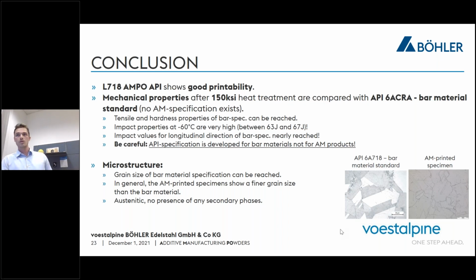So yeah, you always have to consider that this API specification is developed for bar materials and not for AM products. So we can achieve this standard, which is made for bar materials, with our AMPO, so with our AM powder. And in the end, with the microstructure short conclusion, the grain size of bar material can be reached. And of course, the AM printed specimens show a finer grain size than the bar material.